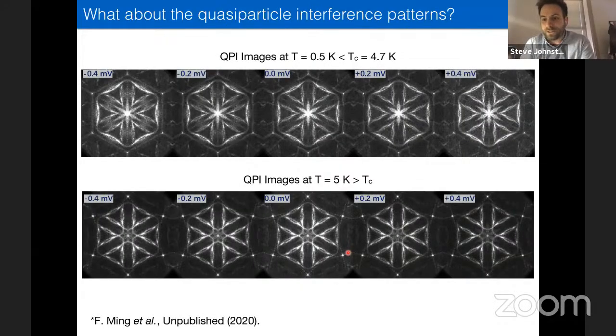there's been a lot of discussion in the literature about how to extract this, but here we're looking at some qualitative features. So what's shown here in the top panel is the experimental data in the superconducting system as a function of bias voltage from minus 0.4 up to 0.4, and this is at a half a Kelvin, which is well below the superconducting transition. The images look a lot like what we saw before. Here's that 2kF image of the Fermi surface. Here's that dumbbell-like feature I pointed out to you.